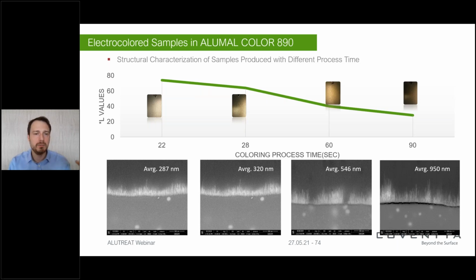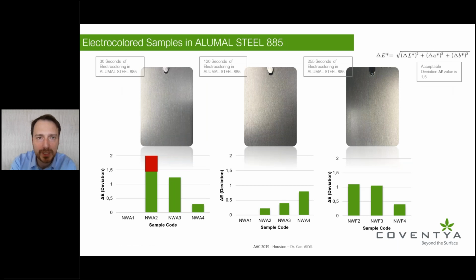We are currently trying to match someone else's sample. Therefore, it is paramount that we choose the chemistry and the coloring parameters accordingly so that we can match the sample. And here what we have proposed is a nickel-based electrocoloring, which we call ALUMAL STEEL 885. So we are not only talking about light champagne right now, but about colors very similar to stainless steel. Quite frankly, the main reason is this is a very low precipitation process. And because it is a very low efficiency precipitation process, you end up with a longer time even with a light shade, which enables you to control your process, quite frankly, almost perfectly.